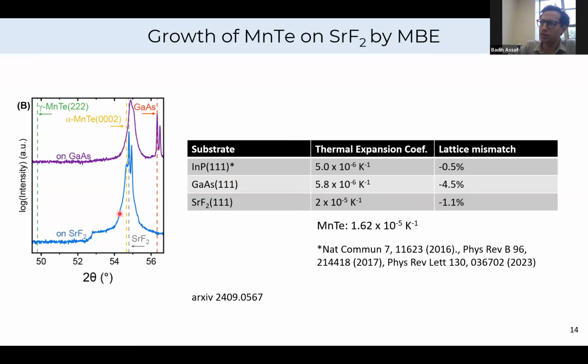And in fact, when you grow thick enough, for the X-ray diffraction pattern that I'm showing here, the film is 100 nanometers, and you can see that it's relaxed. The Bragg peak that we see lies right on top of the expected Bragg angle computed using the bulk lattice parameters. So I'm calling these the pristine samples in a way.